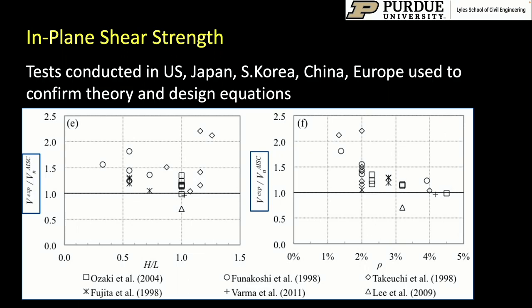Using this equation for the in-plane shear strength, we were able to collect all the experimental data from Japan, China, South Korea, and of course the United States. And we were able to develop a simple equation for conservatively estimating the in-plane shear strength of these walls.